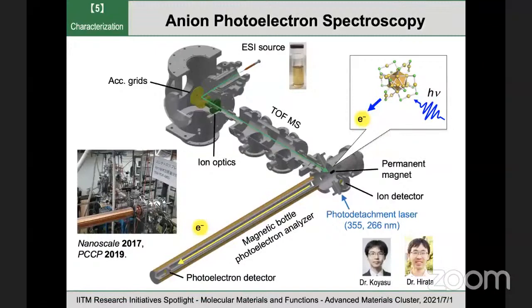This is a photoelectron spectrometer developed in our group. Now we can introduce chemically synthesized clusters in solution into vacuum via an ESI source. And after mass selection, we shine the clusters with laser light to detach electrons from the clusters, superatoms. And by measuring the electron kinetic energy of the photodetached electron, we can record the photoelectron spectrum of the size-selected superatoms. Next, please.